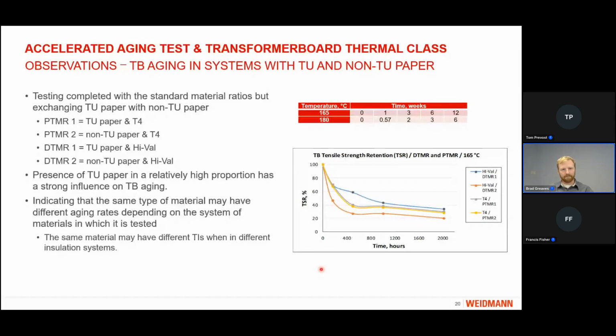So again, what we learned, kind of confirming what we had thought before, the presence of thermally upgraded paper in a relatively high proportion, as seen in the distribution ratio, has a strong influence on the transformer board aging. So this is leading us to believe that the same type of material may have different aging rates depending on the system of materials in which it's tested. We can see that from the aging curves here. The same press board has different aging rates depending on the combination of materials it's aged with. And ultimately, this could lead to the same material having different thermal index when in different insulation systems.